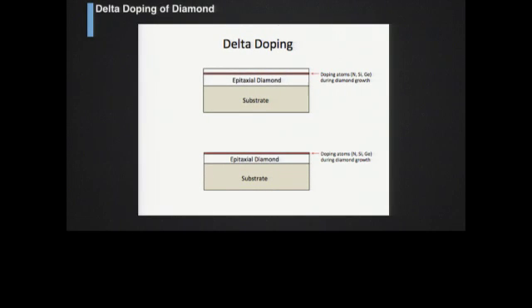What we want to do is, if we want to use nitrogen for some of our applications, we have to develop what we call delta doping. That is, to be able to put a thin plane of nitrogen atoms, NV centers, near the surface, or be able to bury them inside the surface at a certain distance away from the surface. So we've experimented with delta doping. That is, basically we put a plane of nitrogen atoms, or we turn on the nitrogen source for a short period of time during the growth, and that produces almost like a spike impulse delta response in the nitrogen concentration, and then we take a look at the actual profile.